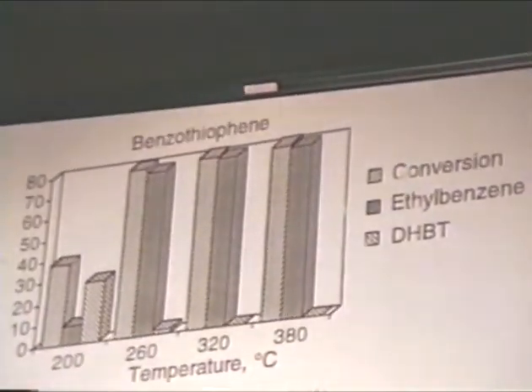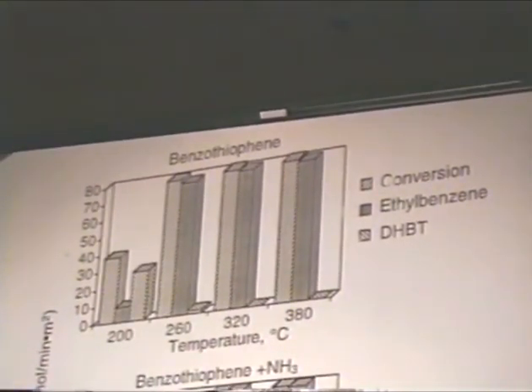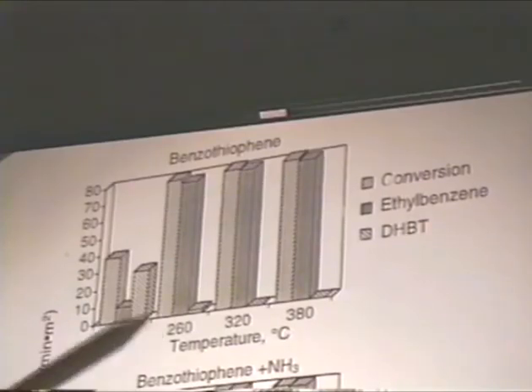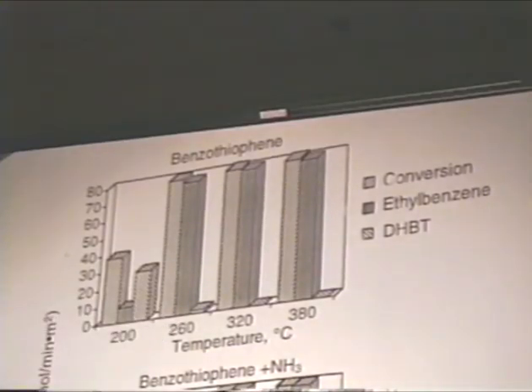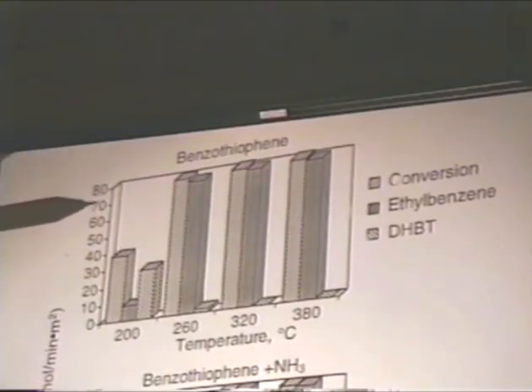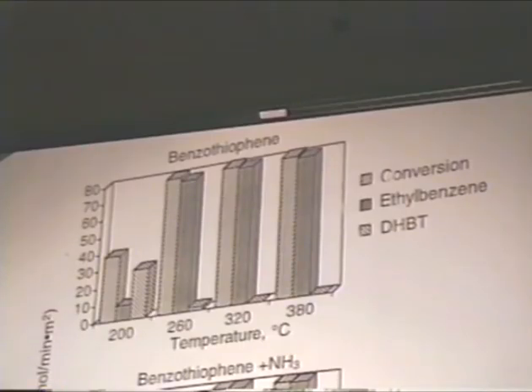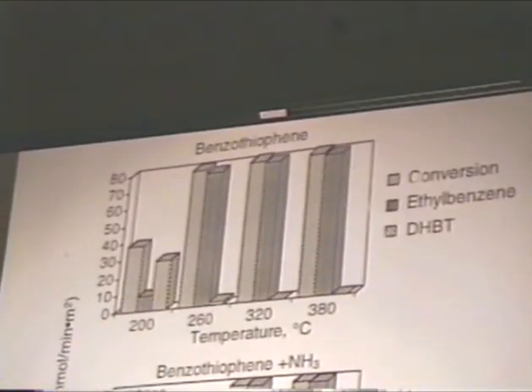Now, if we look at benzothiophene HDS studies at different reaction media, here we are looking at conversion rates and ethyl benzene and dihydrobenzothiophene formation rates. Obviously, these are the observed formation rates as a function of temperature. We're starting with only benzothiophene in the feed system. What we see here is at temperatures equal or above 260 degrees centigrade, we are getting essentially complete conversion. This is where the feed flux is approximately. And also, ethyl benzene formation rate is equal to the conversion rate, meaning we are getting complete desulfurization. At 200 degrees centigrade, we don't have complete conversion. Also, we don't have complete desulfurization. We are seeing significant levels of dihydrobenzothiophene.